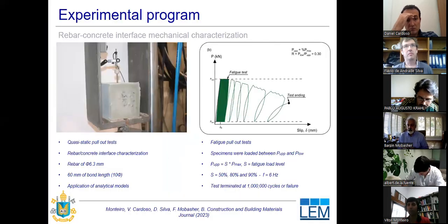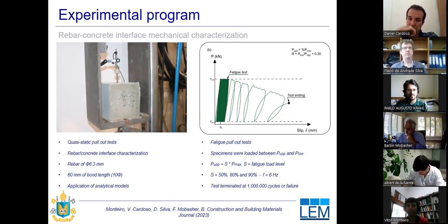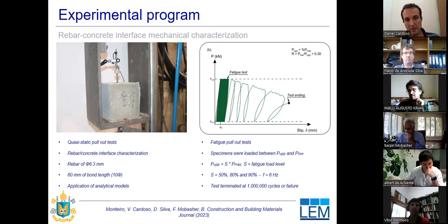So first, the experimental program. We have rebar pull-out tests. We carried out quasi-static pull-out tests of the rebar in the FRC matrix, because we wanted to evaluate the rebar-concrete interface characterization. So we used a rebar of 6.3 millimeters, with 60 millimeters of bond length, which is around 10 times the rebar diameter. After the experimental program, we also applied some analytical models to verify the bond slip behavior in the quasi-static mode. Then we have the fatigue pull-out tests.